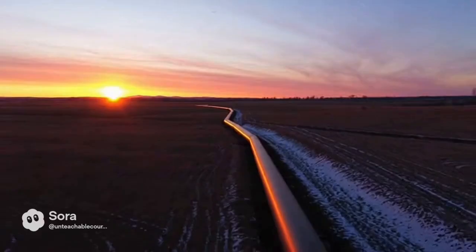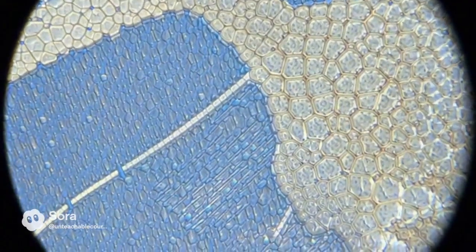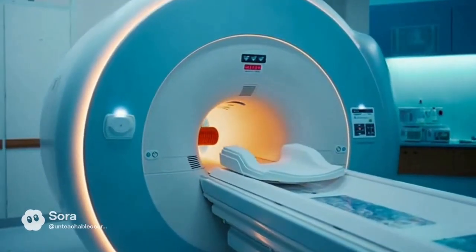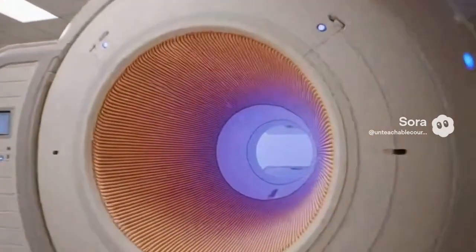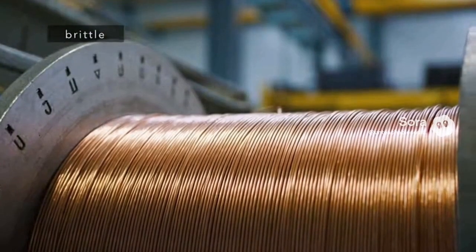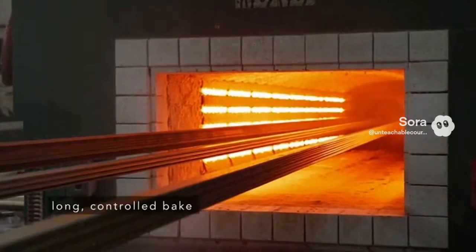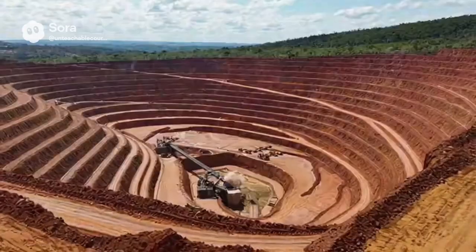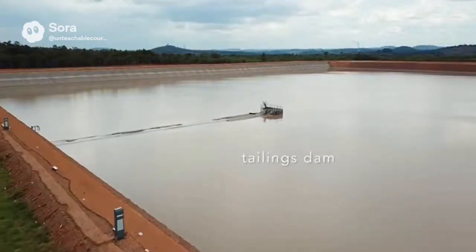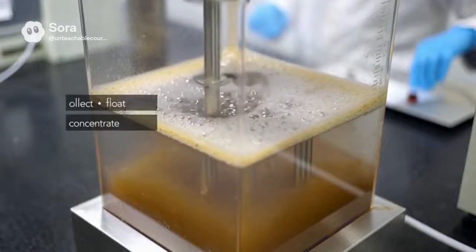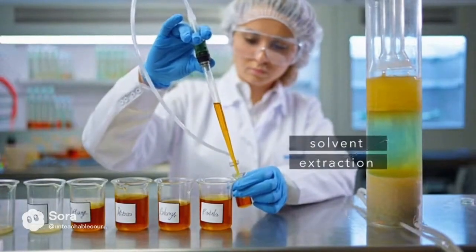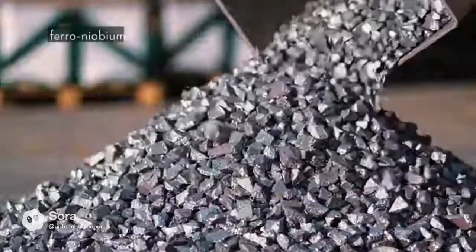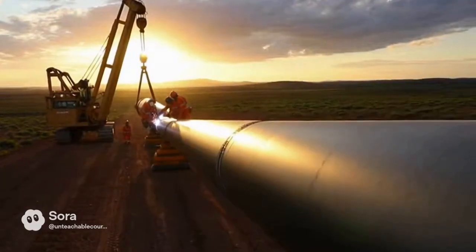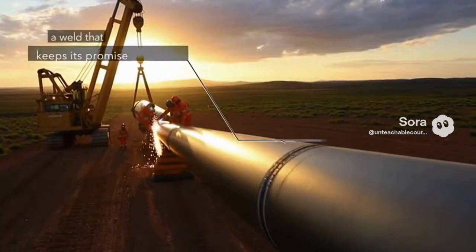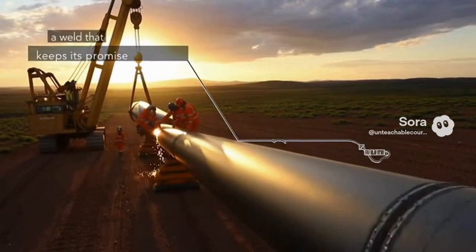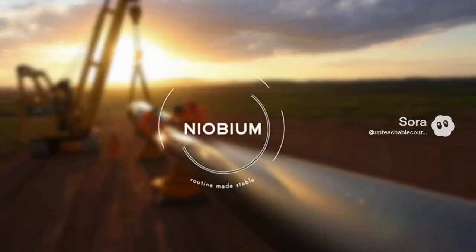Automotive engineers transmute the same physics into different bragging rights. A side impact beam that refuses to buckle early, a B-pillar that lets you meet crash targets without adding a kilogram, a frame rail that stamps cleanly instead of springing back like a bow. The playbook is familiar: solution niobium during hot rolling, a controlled precipitation sequence, and then a transformation path that lands you in a cocktail of ferrite and bainite whose morphology is tuned by the rolling schedule and subsequent cooling. The difference is in the later steps: cold forming, coating, sometimes a press hardening step for components that need martensite at the finish line. Niobium does not object.